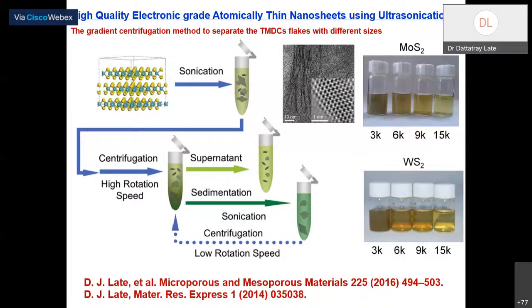And I just do ultrasonication maybe for 1 hour, 2 hours, depending upon, and of course, speed is also important: 3000, 6000, 9000, or whatever. And of course, after that, you can do centrifugation, and you can separate the supernatant material and sedimentation. Once you have separated these things, you can see the change in color contrast depending upon the speed of your centrifugation, 3000, 6000.